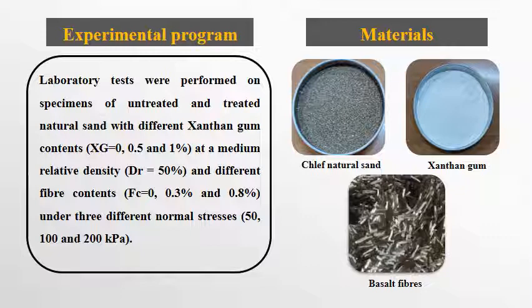The experimental program consists of laboratory tests performed using the direct shear box on specimens of untreated and treated natural sand with different xanthan gum contents at a medium relative density and different fiber contents under three different normal stresses. The materials used were Chlef natural sand, xanthan gum biopolymer, and basalt mineral fibers.